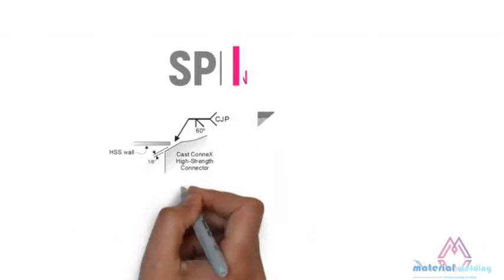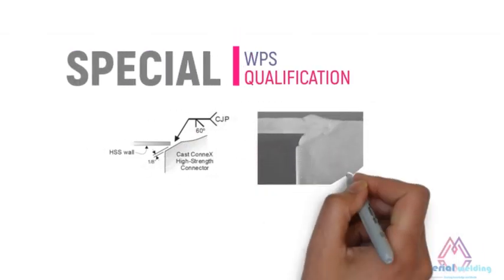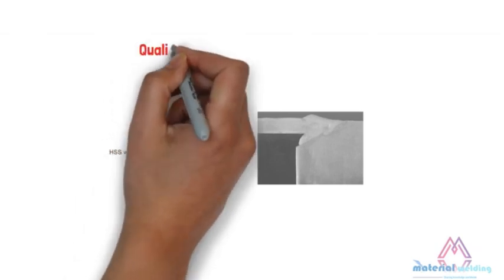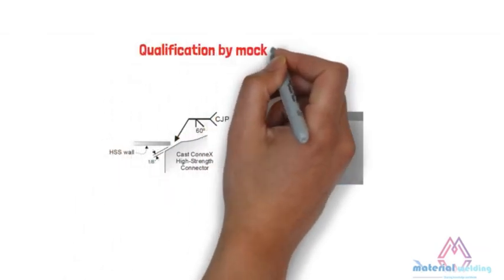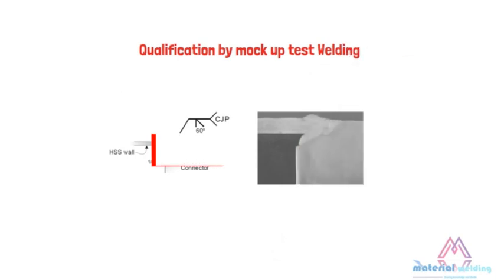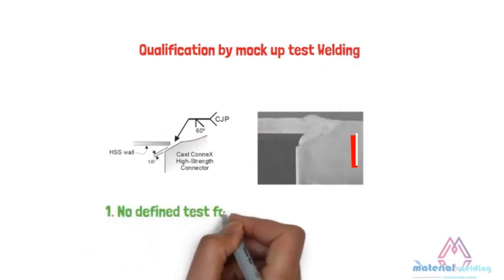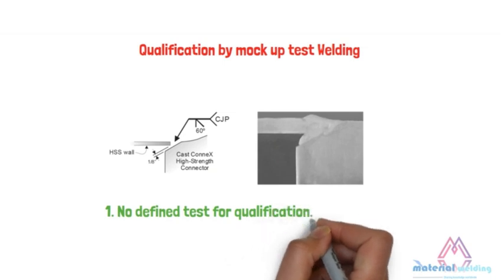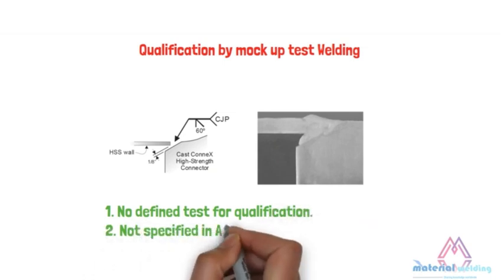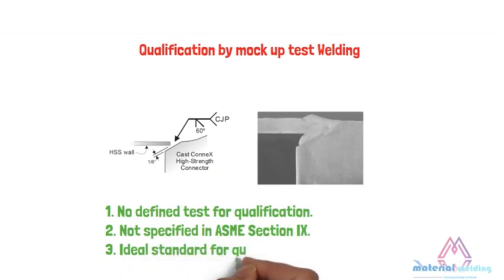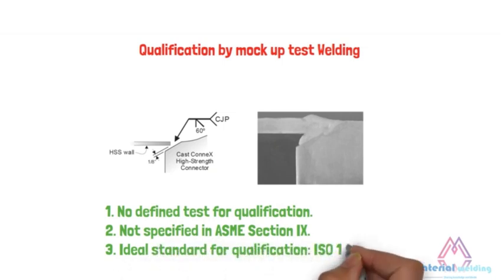At number four is WPS qualified using mock examination. There is no standard format available for these types of WPS. ISO 15613 is a good reference standard for these types of WPS qualification. The WPS format is defined by the customer's need, quality requirement, and welding conditions.